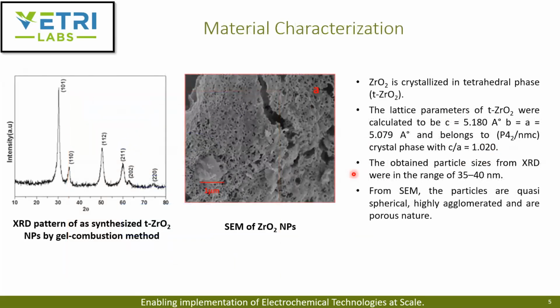On the material characterization side, initially they used XRD to confirm the crystal phase, and what they found was that it is in the tetragonal phase. The lattice parameters were calculated to be around 5.180 for C, and B and A were about 5.079 angstrom, and they belong to the P42/nmc crystal phase. Next, with XRD, they used the Debye-Scherrer formula to calculate the particle size, and they found it to be roughly about 35 to 40 nanometers.